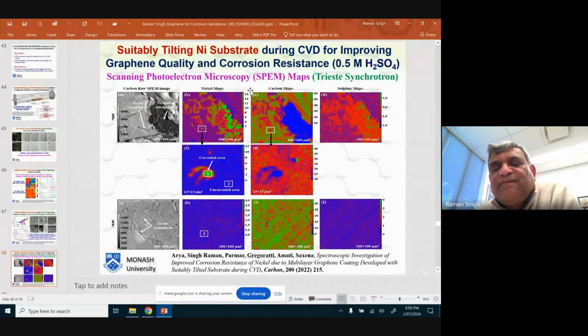The carbon itself, the graphene, was not uniform over the surface. Then you had disrupted areas. So disruption here exposed nickel, which reacted with sulfur, and we could understand it further. Whereas in the 45-degree tilted sample, you can see no nickel signal because we had a very good graphene coating on top. Carbon is very uniformly distributed on the surface, and no sulfur because we didn't have any bare area. So that was about nickel.